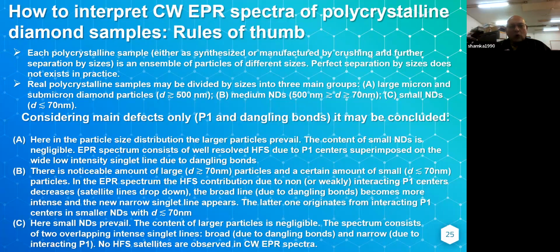One can say that for group A, the larger the size distribution, the larger particles prevail. The content of small nanodiamonds for group A is negligible, and the EPR spectrum consists of well-resolved hyperfine structure due to P1 centers, superimposed on the wide low-intensity singlet line due to dangling bonds. They are there, but not too much, let's say.